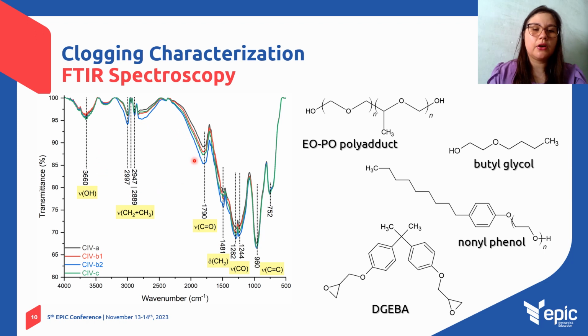FTIR analysis, or infrared spectroscopy analysis, demonstrated similar infrared spectra for all the clogging material samples, A, B, and C, mainly presenting stretching from hydroxyl, methylene, methyl, and oxidized carbon groups, besides bending of methylene groups. These infrared absorption bands can be related to the components present in the chemical injection lines and in the composition of the butylglycol, that is the glycol used to flush the line, and the components of the polymeric demulsifier,